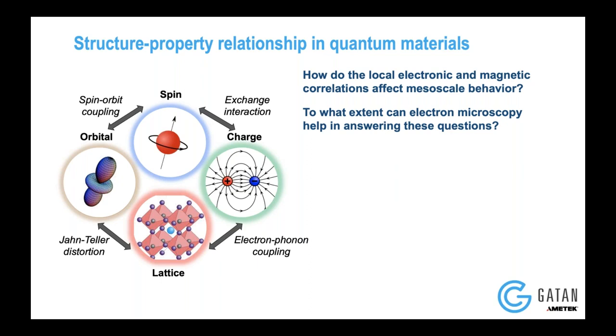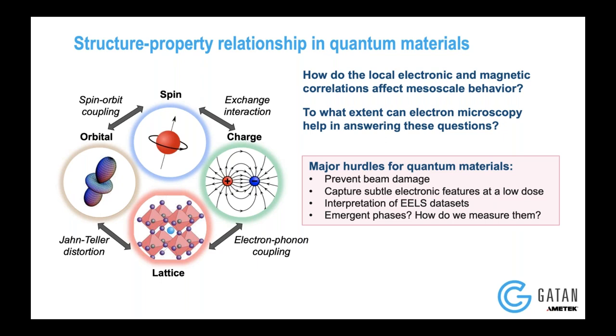I'll be commenting upon how this bubble of limited information about electronic correlations was expanded with the addition of the K3 detector in Gatan. Before the K3 was installed, we had the following hurdles in quantum materials. For example, most of these materials can be beam sensitive — they can have defects formed when you hit them with the electron beam. All of these degrees of freedom have very subtle effects, so you need an instrument that detects very subtle signals. That's where K3 was beneficial.